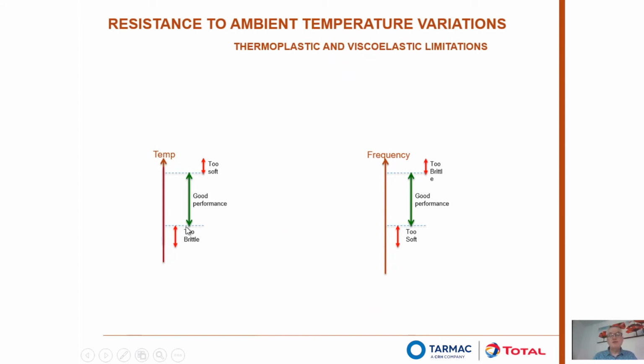So if you look at this graph here with a penetration grade bitumen, you have a range of temperature where you're getting good performance. But then you have a critical temperature above which the bitumen is really just becoming too soft. It's still got some solid contribution, but it's a little bit too soft to fully resist the engineering forces that are being applied to it. Similarly, at lower temperature, the solid impact is starting to take over and it's starting to become too brittle. So you have a range of temperature here at which you have good performance, good engineering contribution. Above that, it becomes too soft, and below this critical temperature, it becomes too brittle. Well, of course, if we're talking about climate extremes, we could well be, in hot summer periods, delving into this area where it's too soft for penetration grade bitumen to cope.